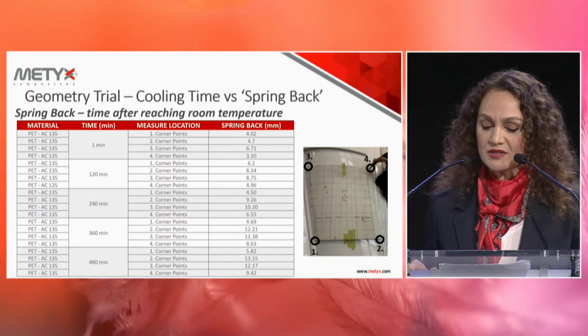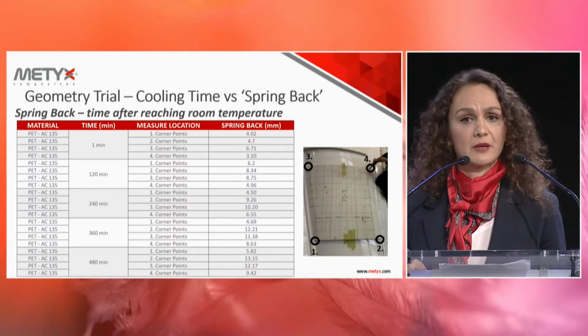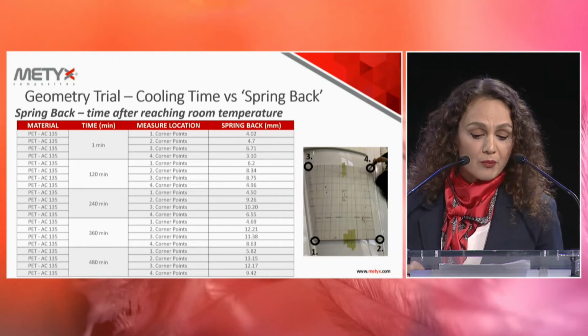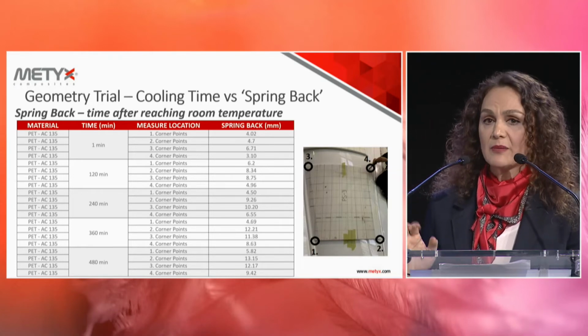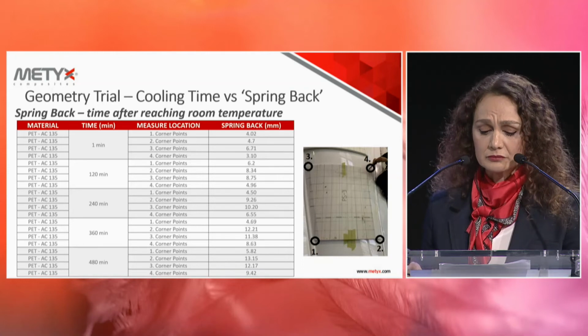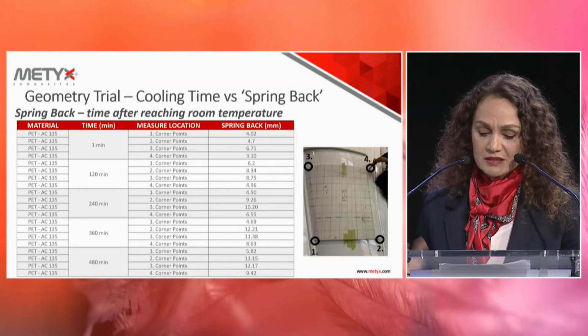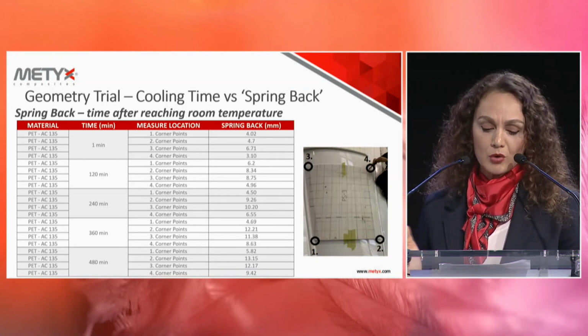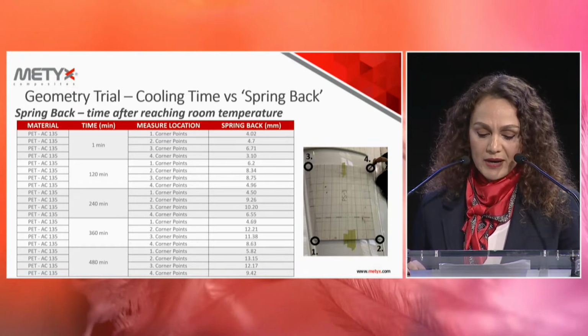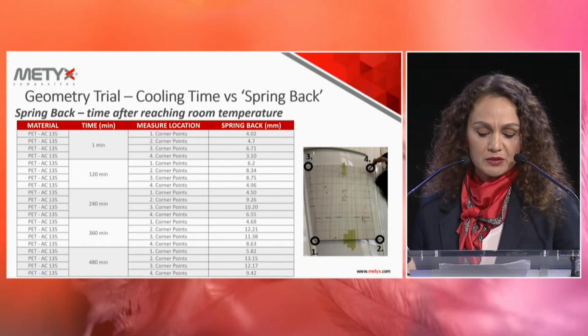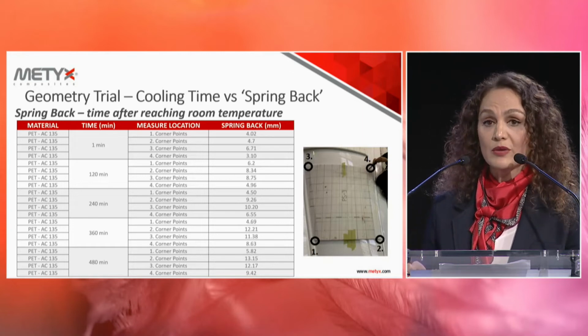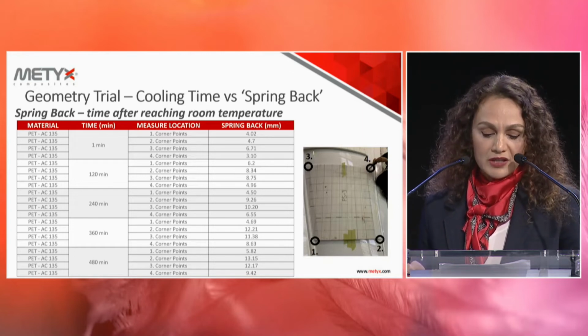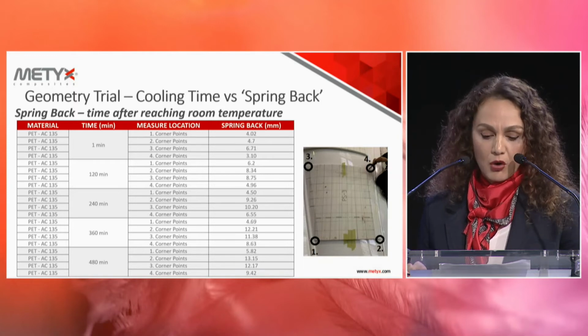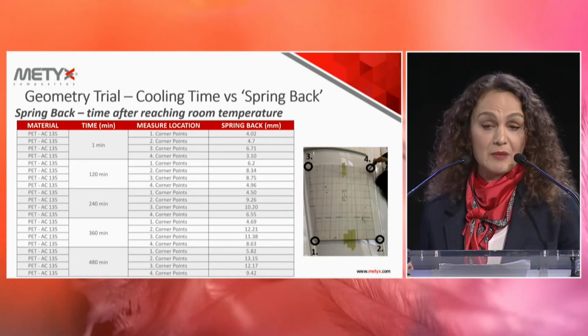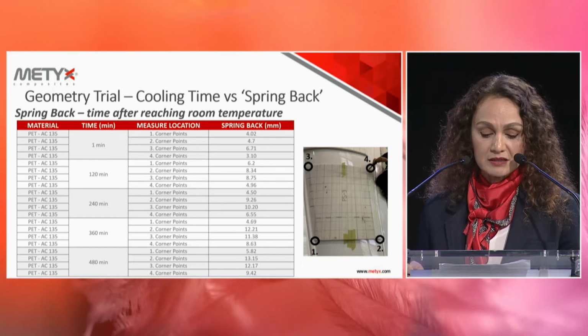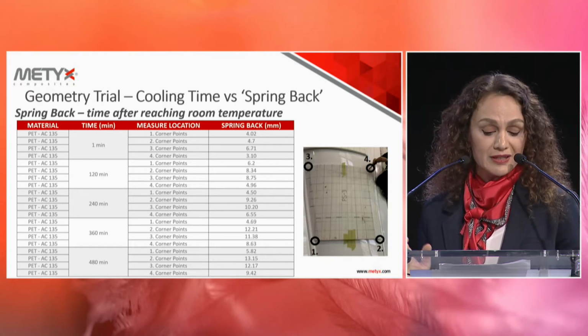If we look at the result, we see that the spring back after reaching temperature, after 1 minute, was not too much. It changed between 3 millimeter and 6 millimeter. Point 3 is 6 millimeter, a little bit more aggressive than 1 and 2. So after 1 minute, you see it is pretty acceptable because we can pull it back down with the vacuum bag. We can make the fabric align with the core, even at 6 millimeter. So we can bring it back to its original shape around the mold with little problem.